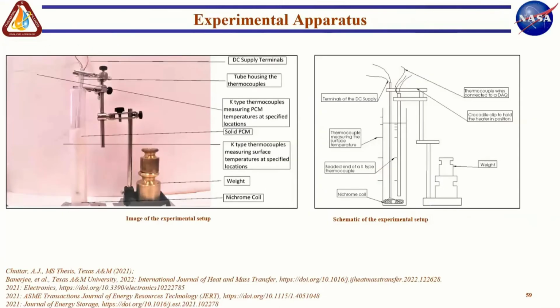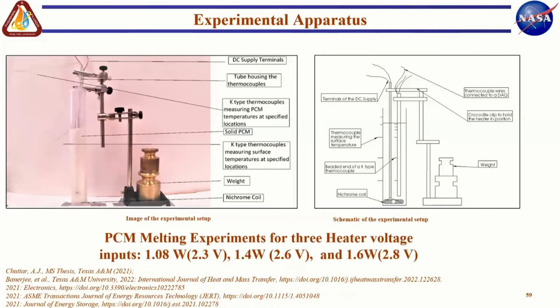So this was our experimental apparatus, the picture on the left, the schematic on the right, where we mounted thermocouples at different heights within this measuring cylinder. We put a nichrome coil at the bottom of the cylinder to melt the PCM from the bottom. And we measured the temperature time trace of these thermocouples for 3 different power inputs to the nichrome coil, at 2.3 volts, 2.6 volts, 2.8 volts, 1.08 watts, 1.4 watts, and 1.6 watts essentially.